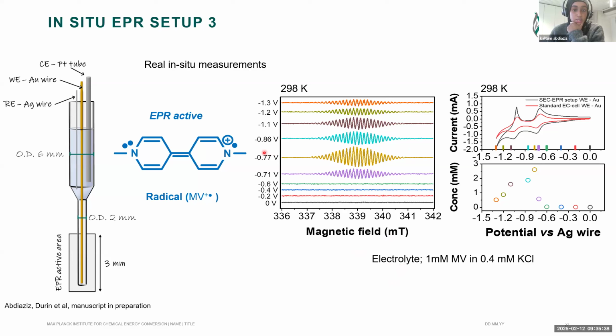What I did was apply several different potentials and then measure their corresponding EPR. If you look here at the CVs, I compare a standard electrochemical setup, which is red, and my setup here, which is black, and they agree very well together. So again, I'm sure that my setup is working like an electrochemical setup should work.